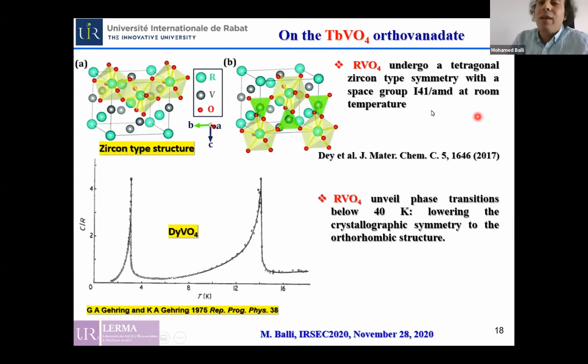This tetragonal structure transforms into an orthorhombic symmetry at temperatures below 40 Kelvin. This crystallographic transition is usually associated with a Jahn-Teller effect due to the strong coupling between the electronic order of the rare earth element and the crystallographic structure.